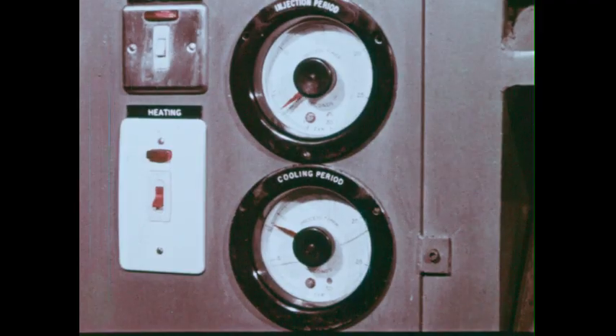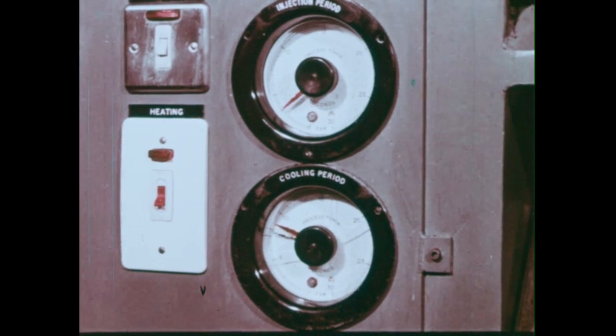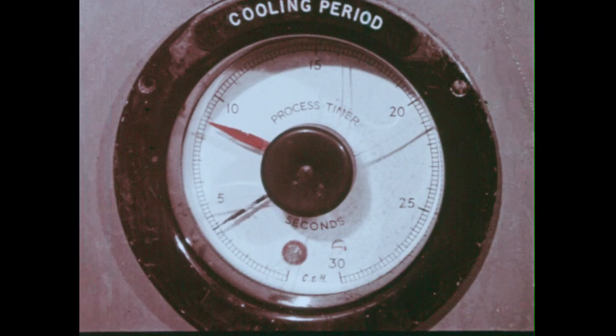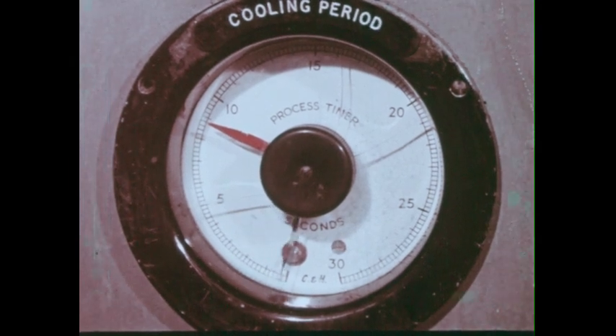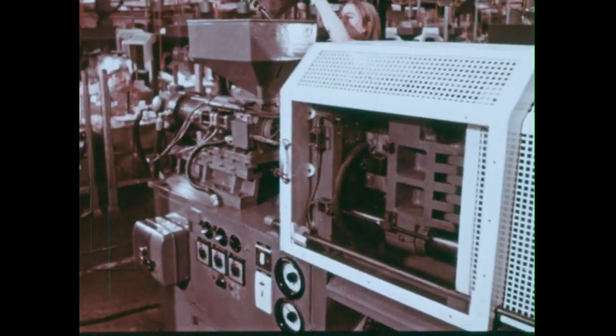This is a new type of rubber, revolutionary in that it doesn't need vulcanizing. The tires are made by straightforward injection molding, just like plastic. In fact, what we have here is a totally new class of material, thermoplastic rubber. Each molecule is a 3-block copolymer, polybutadiene in the middle and polystyrene in the tails. In large numbers, the tails associate into clusters or domains. They link the polybutadiene chains and give the rubber stability, the job normally done by sulfur.